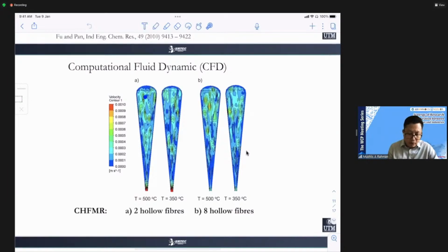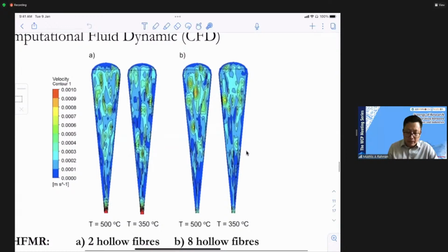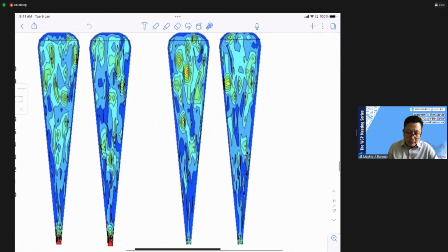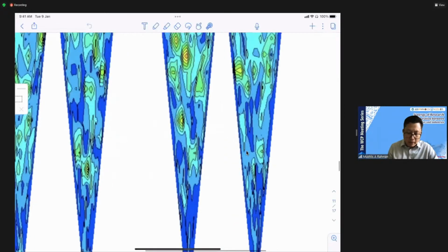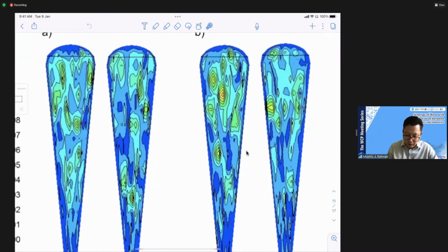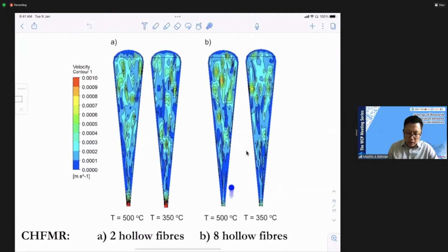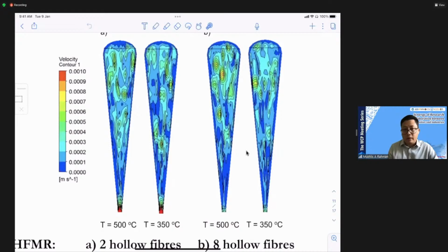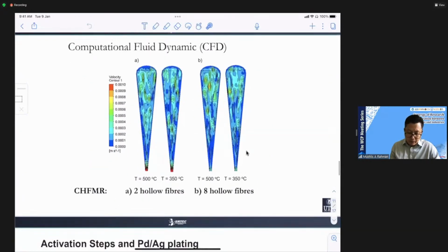So from the figure in here, you can see that a lot of vortex flow occurs. Okay, let me make it bigger. The high velocity is represented by the yellow. You can see that over here. The more hollow fiber you put, and the higher the temperature, the more vortex flow can occur. Okay, this is good for our system. It means they improve the mixing process inside the ceramic hollow fiber membrane.